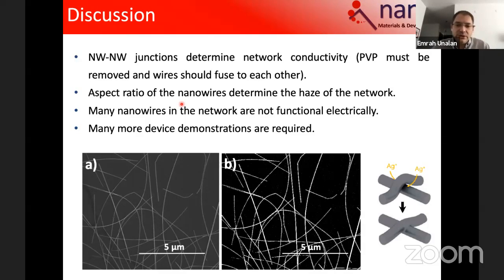And we see in the papers that nanowires thinner than 50 nanometers are not that stable in ambient conditions due to the strain effect. And so this is a sacrifice again, they cannot be thinner than 50 nanometers, but if they are thicker, haze also comes along. So if you're going to make use of these materials for a transparent conductor, you have to pay attention to the haze factor. So thickness and the haze are competing with each other in this regard.